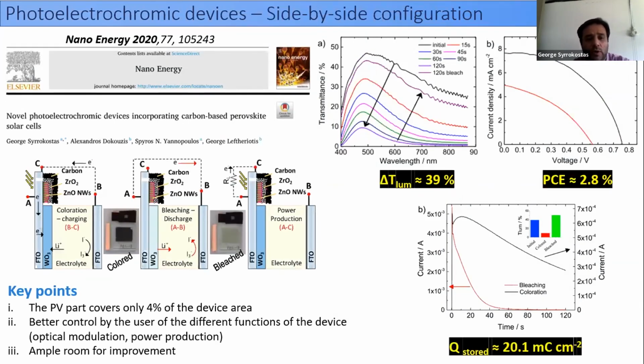Also, 2 years ago, we used a carbon-based perovskite solar cell to power the electrochromic unit of a photoelectrochromic window having a side-by-side configuration. Here, the PV unit covered only 4% of the total device area. That means that in the previous cases, the coverage fraction was 20% or 15%, and now we have less area of our device that is optically inactive. In this case, the transmittance modulation was around 40%, and the photoconversion efficiency reached 3%.